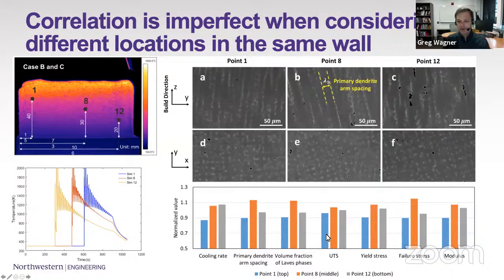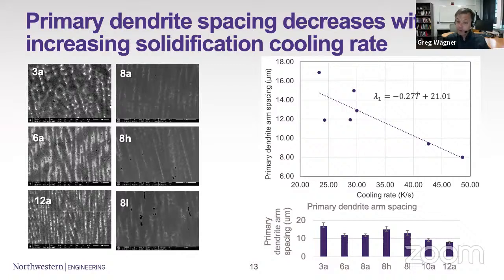But pretty clearly the strength is different in the middle of the wall compared with the other points. And this is a trend that we see across multiple walls in different locations. And so for some reason, the cooling rate by itself is not such a good indicator. It is for the points, and let me remind you, we have mechanical testing data for all of those, order of 100 points, samples across the walls, but we only have microstructure measurements for a subset of those.